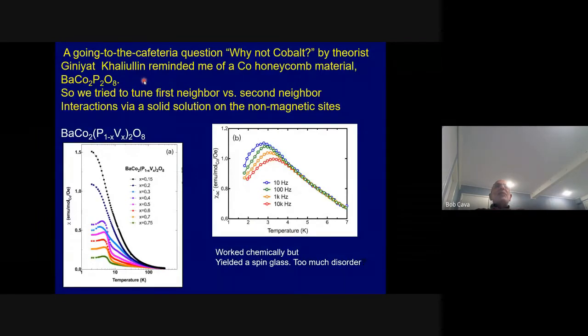So what about BaCo2P2O8 or BaCo2PO4 2, depending on how you write the formula? Why not try to tune that one to see if you can get to this quantum spin liquid? Well, it doesn't work. And the reason it doesn't work, we tried it by changing the thing on the tetrahedron. And the tetrahedron is off the magnetic site, so you expect that it's okay to do chemical substitutions on that site, but it doesn't work because of this weak off-site disorder. So that didn't work.